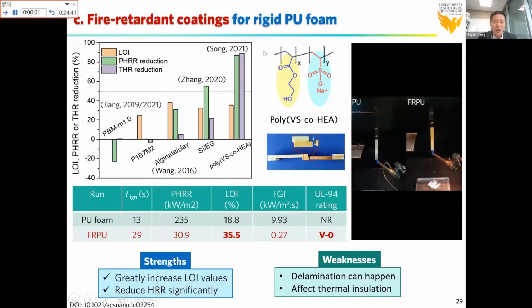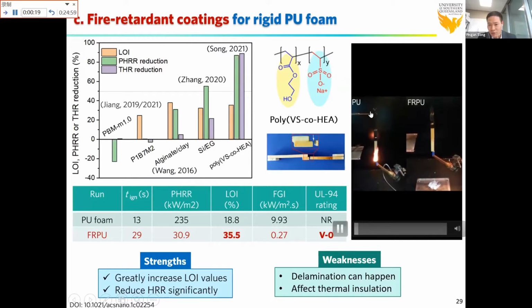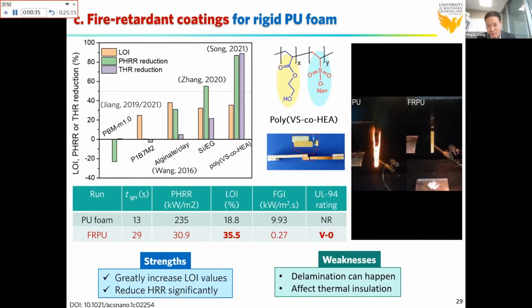So the last strategy for PU foam is flame retardant coating. Not many people are working on flame retardant coating because it requires high interfacial bonding. But this is a copolymer we have recently developed. So we can show you these results. The left is the untreated PU foam. The right is the flame retardant coated PU foam. You can see the untreated one burns very fast, and this one is self-extinguishing or you cannot even ignite it. So you can see its LOI is very high. It's 35.5 with a V0 rating.